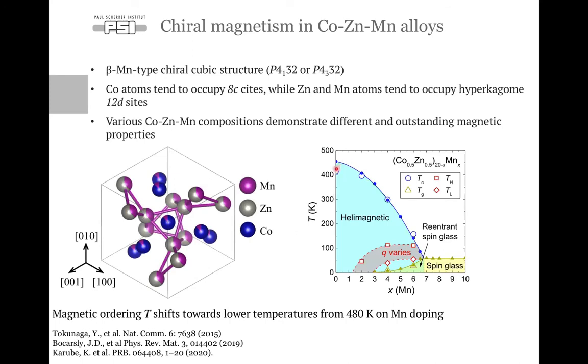In this figure, I show you the phase diagram of magnetic structure depending on temperature and manganese concentration, where for lower manganese content or higher temperatures, the helimagnetic state is dominant, while as we dope the system with manganese or decrease the temperature, due to the frustrated three-dimensional lattice, the Q vector variation starts to develop, and the periodicity of the magnetic spiral changes with temperature or with manganese composition. And by doping the system with more manganese ions, we can suppress the magnetic ordering altogether and end up with a spin glass state for the compositions of cobalt, zinc, and manganese 7 or above.